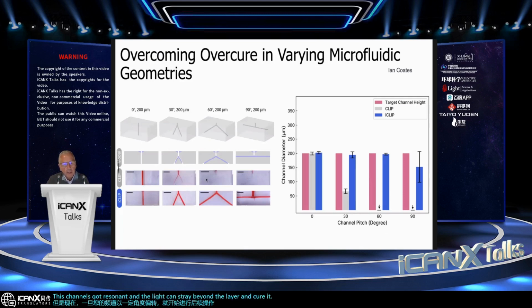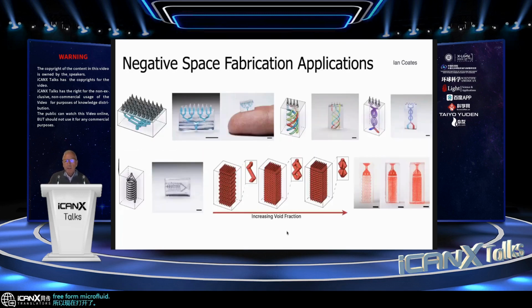And you can see that the channels become cured, and there's no channels anymore. But as you flow resin through, even at 90 degrees, we can keep the channels open. And so now this opens up free-form microfluidics. Really amazing space to play now.